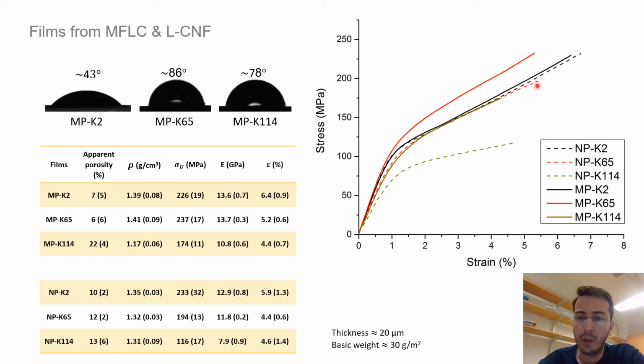And the nanopapers, you can see they are not stronger than the micropapers. One reason is that their porosity happens to be a little bit higher than the micropapers in the sample preparation. But when it comes to a nanopaper with kappa 114, you can see this is really weaker compared to the rest of samples.